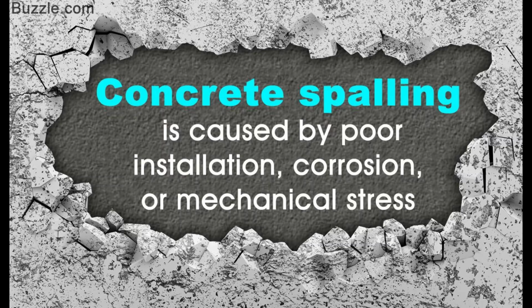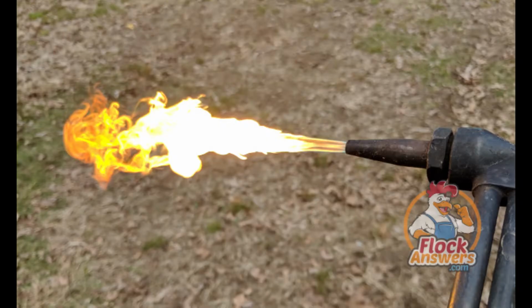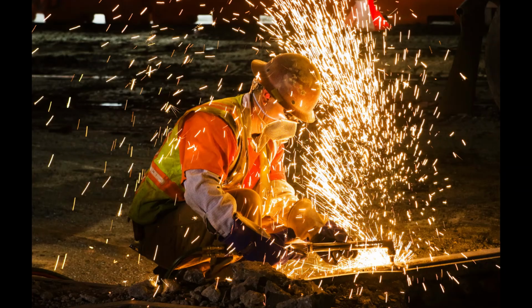It'll start to pop or degenerate and break, especially if, for example, you're cutting over top of concrete with, say, a cutting torch. Then there's every likelihood, especially if you're not very far away from that concrete, that just the slag falling on there or the heat from the torch tip is going to cause the concrete to fundamentally change internally. And the effect of high heat temperature on concrete is such that the abrupt temperature changes can cause cracking and spalling due to this thermal shock and aggregate expansion, and can also produce distress within the concrete.